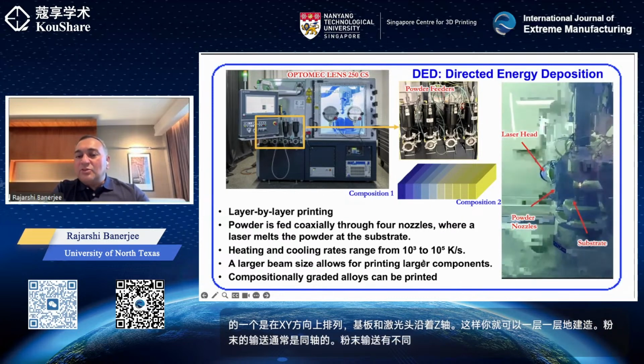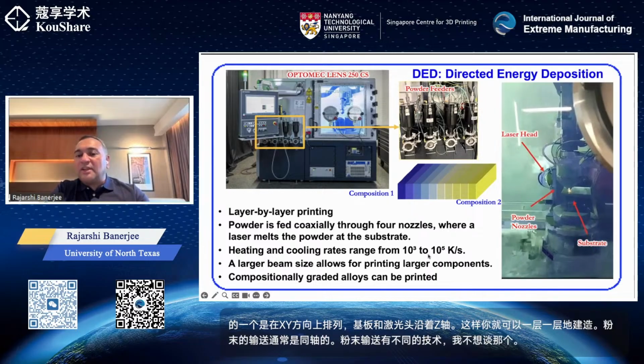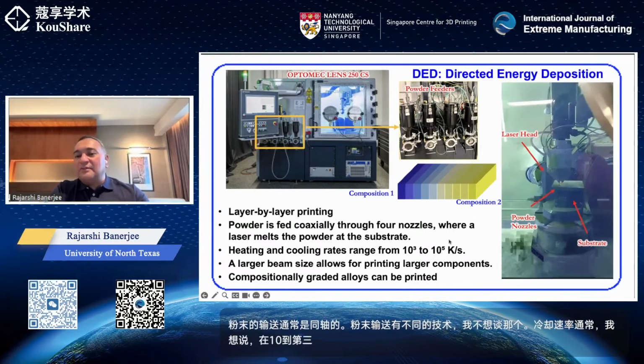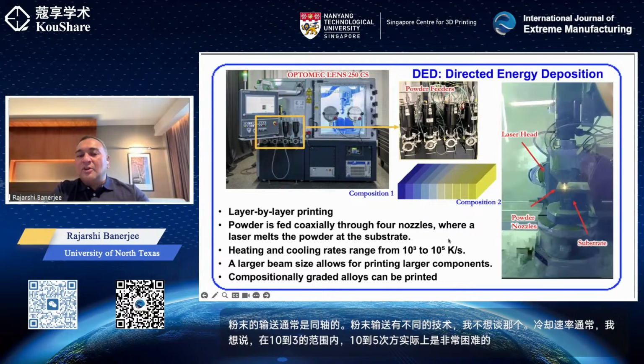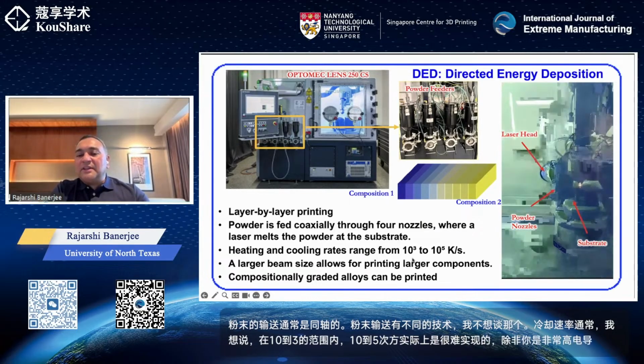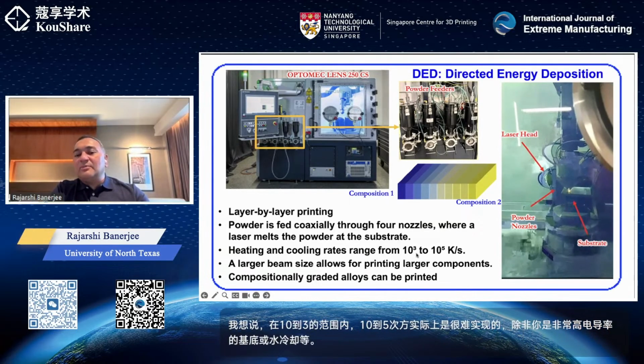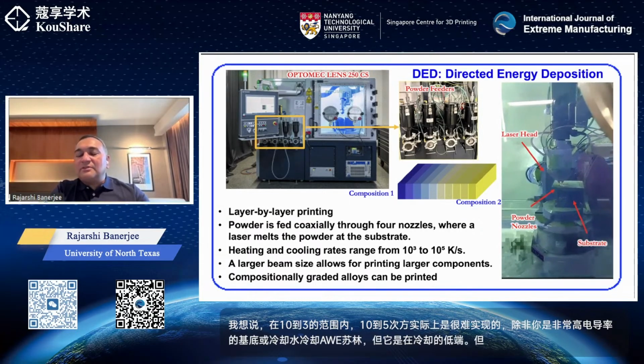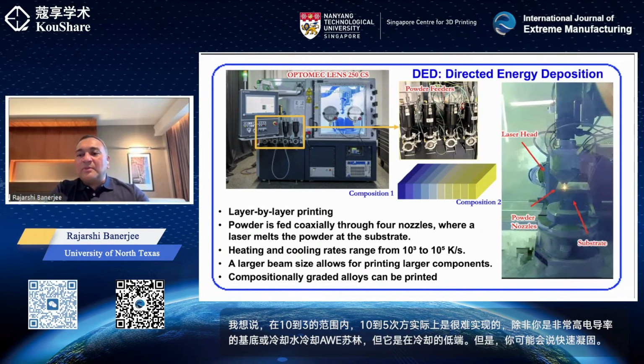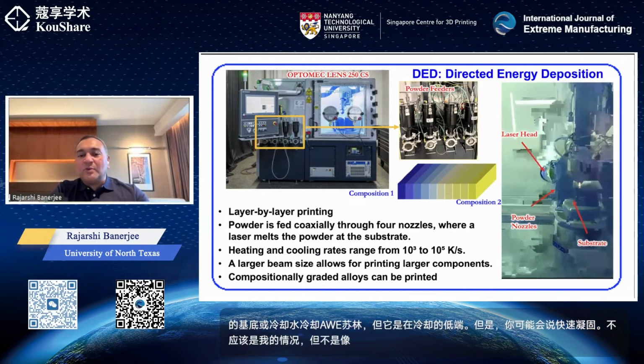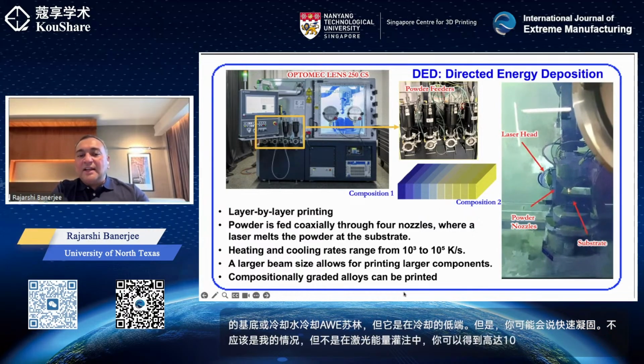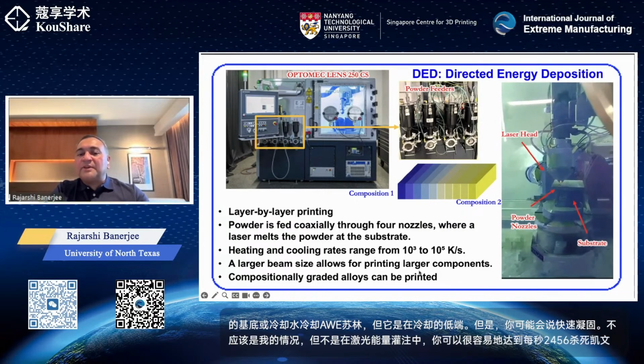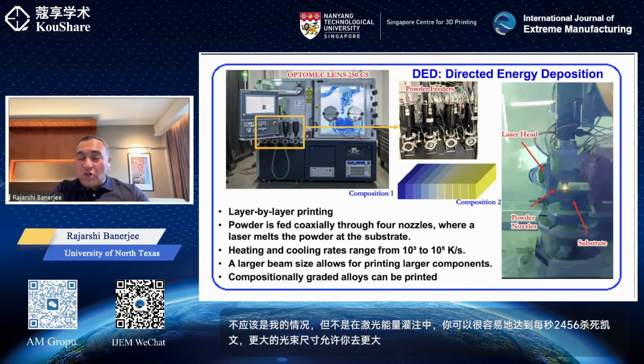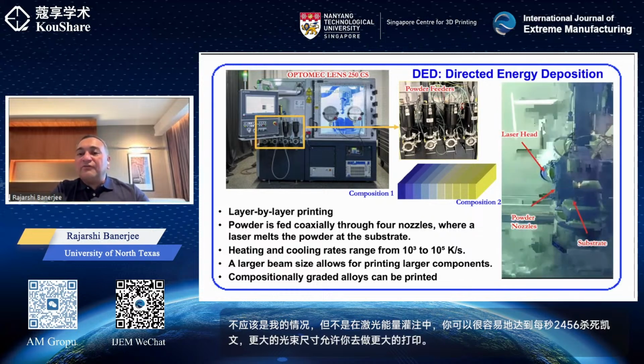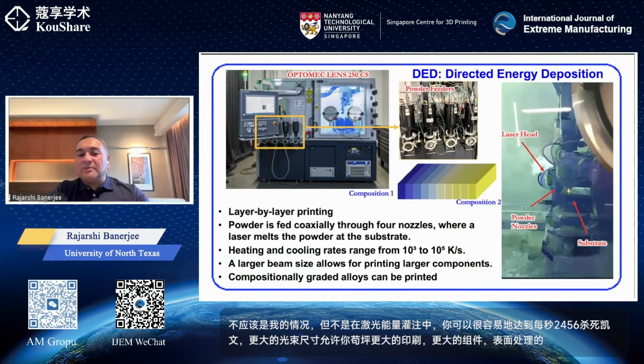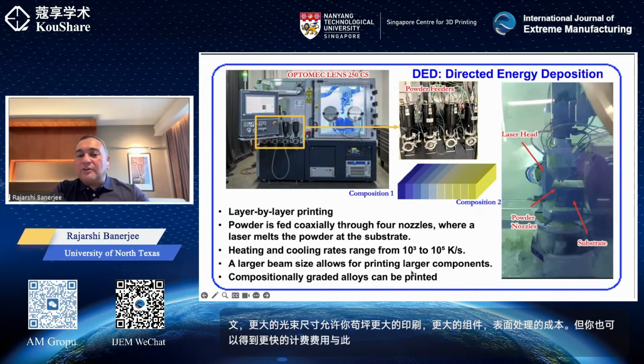Cooling rates are usually, I would say, in the range of 10 to the power 3. 10 to the power 5 is actually very difficult to achieve unless you have a very high conductivity substrate or cool water cooling or so on. But it is in the lower end of cooling, but still you might say rapid solidification type situation, but not as in laser powder bed fusion, where you can get up to 10 to the power 5, 6 quite easily, Kelvin per second. A larger beam size allows you to go for larger printing of larger components, of course at the cost of surface finish, but you can also get faster build rates with this compared to laser powder bed fusion. And it's a very good technique for compositionally graded alloys.